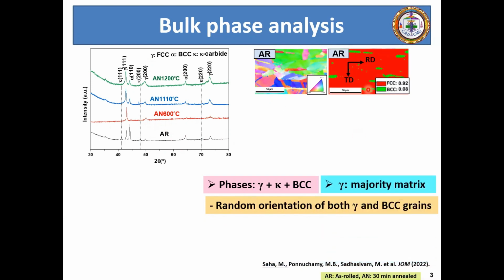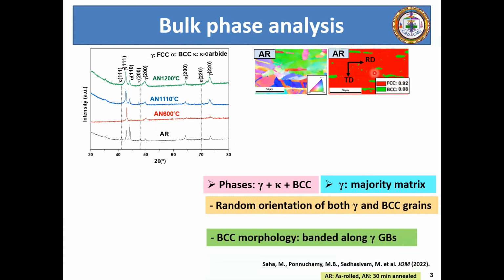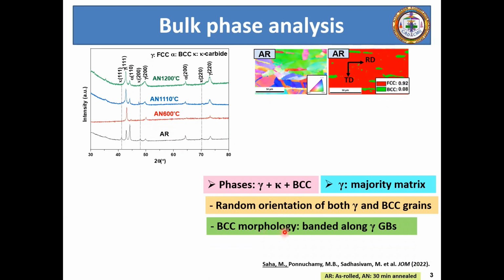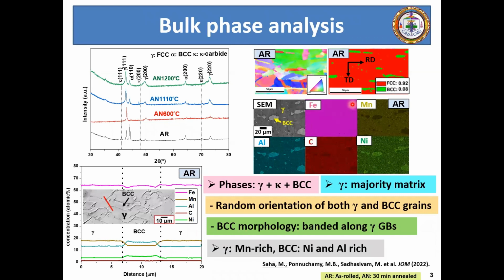Now the corresponding phase map shows that the gamma is the majority matrix with a volume fraction of nearly around 92%. And also, when we correlate the information from both these maps, we can clearly observe that the BCC has a banded morphology and is mainly present along the gamma grain boundaries, and besides, it is also elongated along the rolling direction. So now with this, we have also further performed the SEM EDS analysis in the as-rolled condition,